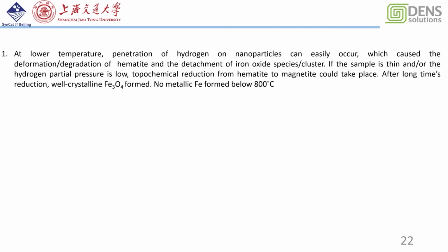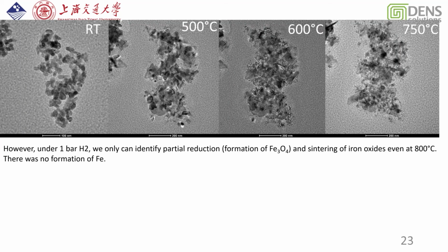So in that case, we can see that this process is completely dominated by the hydrogen diffusion and penetration, and the deformation and the degradation happened at the high pressure, which means not at the atmospheric pressure. But the interesting thing is, even when we increase the temperature to 750 degrees, we cannot get any formation of the metallic iron. So compared to the phase diagram, the condition is extremely high, but the reduction is very, very difficult to get metallic iron. And this is the process.